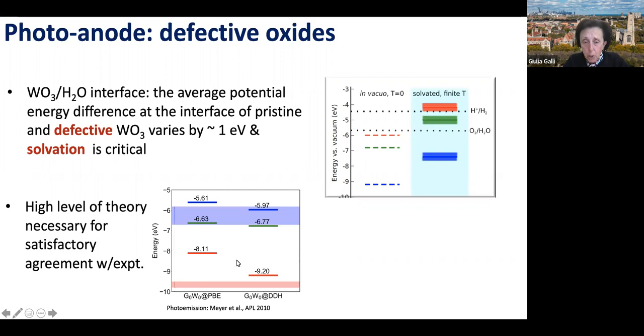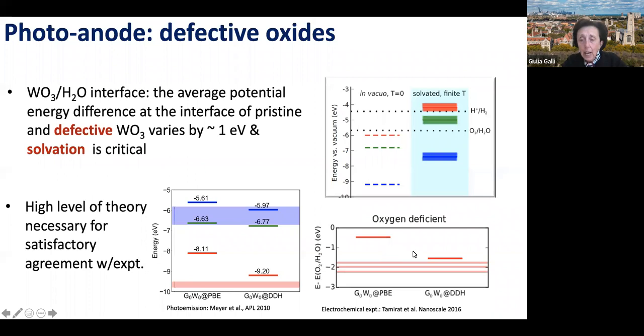So these are some results about the position of the energy levels. The pink and purple are the measurements, and as you see, there is a variability there too. And I'm showing the differences that you get by doing GW calculations starting from semi-local or hybrid functional. And this is our comparison of the flat band potential with experiment, the pink lines, for oxygen deficient surfaces, showing that we have something which is very reasonable. Again, nothing in this field is perfect, but it's reasonable and you can use it to actually make physics considerations.